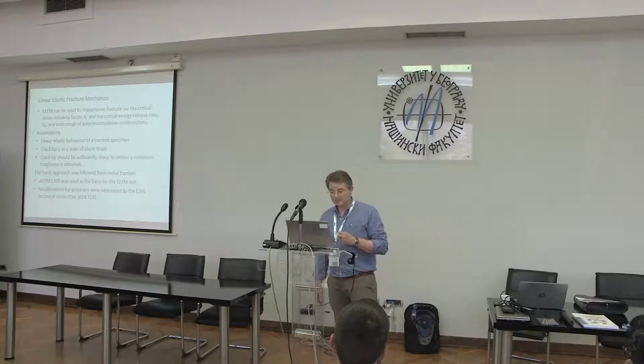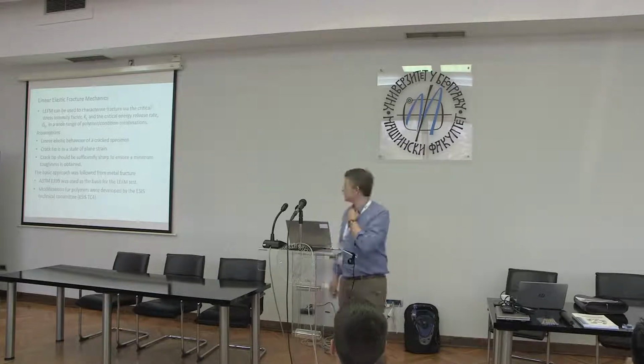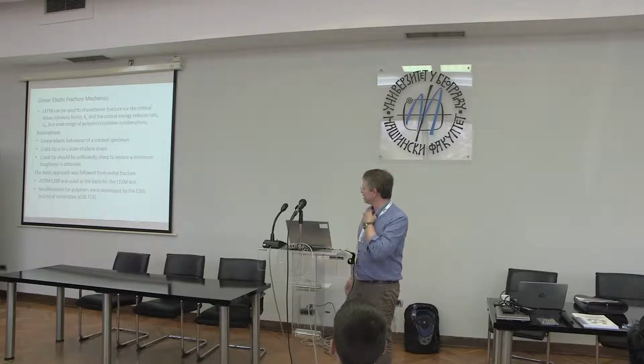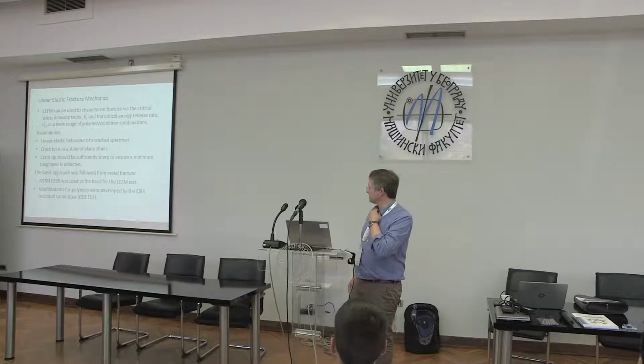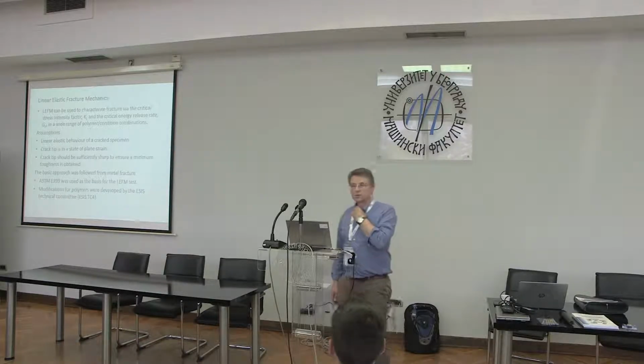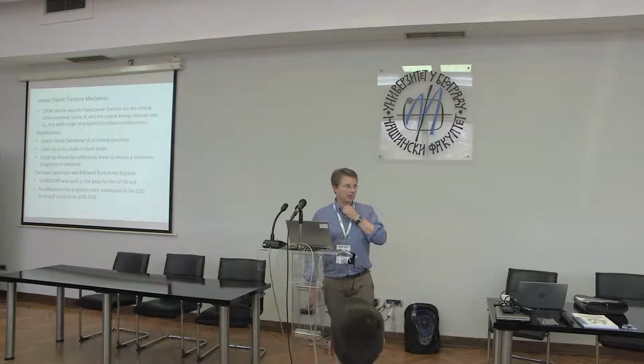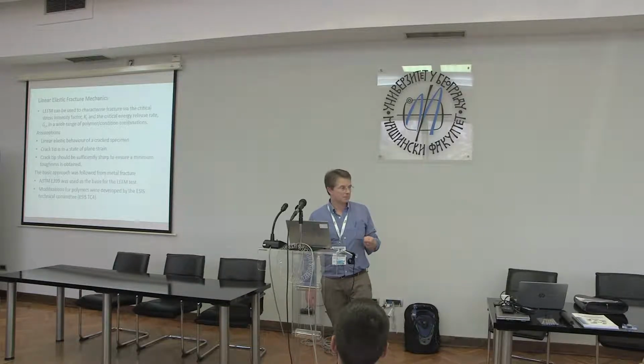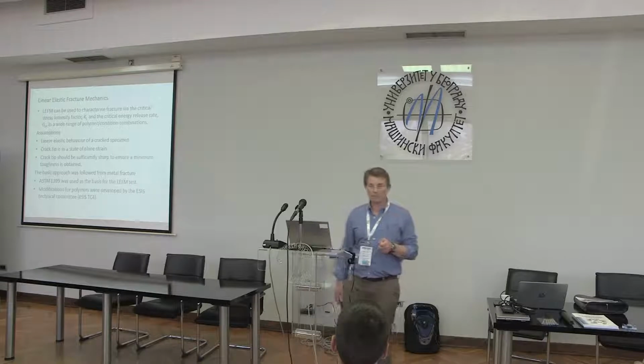we define G. Of course, if we're using LEFM, we're basically assuming that we have linear elastic behavior of the specimen. The crack tip is in a state of plane strain, and the crack should be sufficiently sharp to ensure that a minimum toughness is obtained. Now, this is a really big issue. Okay, so how sharp should a crack be, and how sharp is sharp enough?